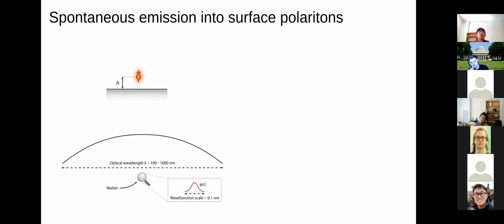Another way to think about this too is how I like to think about the dipole approximation, which is that, from a semi-classical analogy, spontaneous emission of an atom is a lot like an antenna emitting radiation. And it turns out that atoms are really terrible antennas because the wave function of the atom is on the scale of angstroms or maybe a nanometer if you're lucky, whereas even if you're emitting high frequency radiation like ultraviolet, that puts you at like 100 nanometers, which is way bigger. And if you're emitting something like visible or infrared radiation, that's even way bigger. And if you're trying to do it with radio waves, then you're pretty much screwed. So basically, by shrinking the optical wavelength, you're still going to be a lot bigger than the wave function of the emitter, but you can at least put yourself in a situation where it's better.